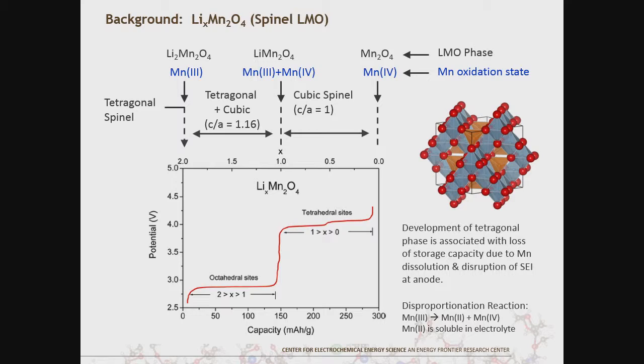Essentially, this is the part of the phase space which is accessed. This transition here, where you nucleate the tetragonal LMO phase, is associated with various complex reactions. This is where you're getting manganese 3 in the system, and manganese 3 is susceptible to disproportionation reactions, which can lead to manganese 2, which is then soluble, which can then lead to manganese dissolution.